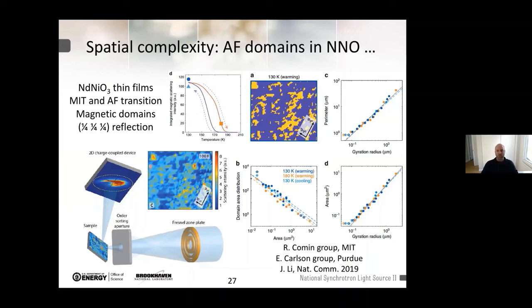And we use this neodymium nickel oxide thin film across its metal to insulator and antiferromagnetic transition to check one of the families of the domains, the 1/4, 1/4, 1/4 reflection, available inside our Ewald sphere at the nickel L3 energy, and to check how they evolve and what are the statistical parameters and how they are distributed versus temperature versus cycle. This was done in a very fruitful collaboration that is still continuing with the Riccardo Comin group and Eric Carlson at Purdue. And you can see that if you consider some of the statistical parameters and their distribution, you will discover that they are distributed among some power laws, that they follow some specific cyclicity or not compared to the thermal cycle that you apply.